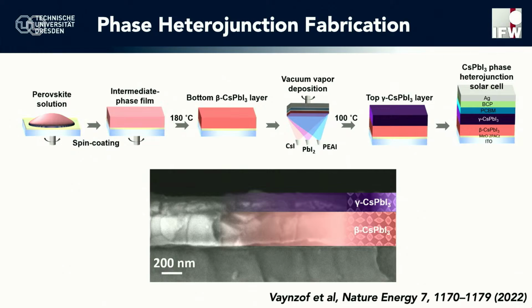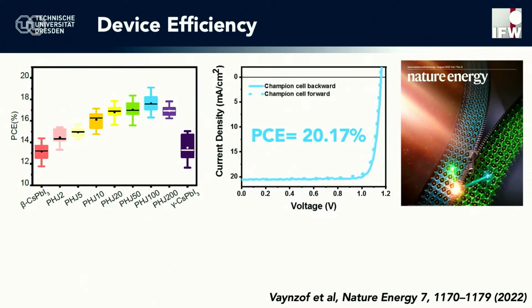So here we used thermal evaporation to deposit cesium lead iodide in the gamma phase. And you can clearly see here in this cross-sectional electron microscopy image that you see distinct 2 layers of the material, the underneath one in the beta phase and the top one in the gamma phase. Now, once integrated into devices, we observe something remarkable. The single-phase devices, you can see here in red the beta phase, and in dark purple the gamma phase on its own. Single-phase devices reach at most about 15% in power conversion efficiency.